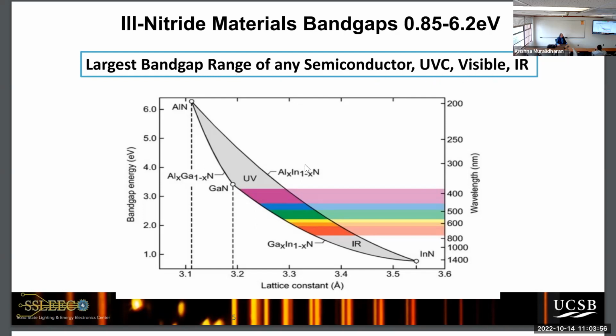It spans the entire visible spectrum. So that means if you take gallium nitride and you alloy it with indium nitride, if you just add 20% indium to it, you get blue. You add 27%, you get green. And if you add about 35%, you get red. So just think about that. All you have to do is add indium to the crystal and you get all these colors. So it's the only semiconductor material system which spans this visible spectrum.